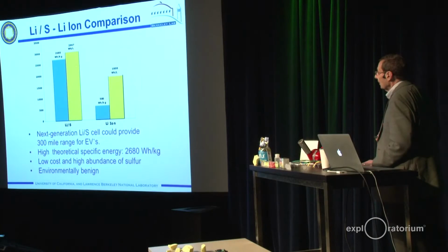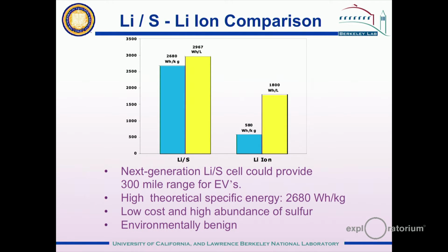The advantage of lithium sulfur on a volumetric basis is not as great as it is on a weight basis. We have 1,800 watt-hours per liter for lithium-ion cells and something approaching 3,000 watt-hours per liter for the lithium sulfur cell. So the advantage is a little less than a factor of 2 in that situation. But a significant advantage is the fact that the materials in the lithium sulfur cell are environmentally benign. Lithium ion cells contain transition metals, among them cobalt and nickel, and both cobalt and nickel have toxic features, and the cobalt is very expensive. Cobalt costs about $20 per kilogram, and sulfur costs less than $0.50 per kilogram.